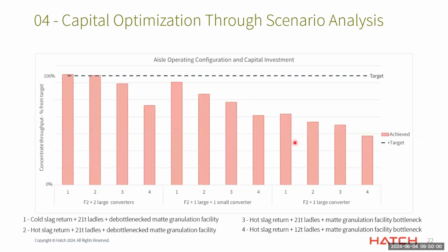Then another valuable exercise was the capital optimization. So we identified 3 optimization opportunities and wanted to review the impact on our operations and throughput should those opportunities be realized. So the first is the removal of the converter slag granulation facility and incorporation of the hot slag return operation that is currently existing at Zimplats. And then the second is deferring to debottleneck the matte granulation facility by upgrading equipment and increasing capacity. So essentially operating the expanded operation with the existing matte granulation facility as is. And then third is to use the existing 12-ton ladle fleet at Zimplats for the full expansion.